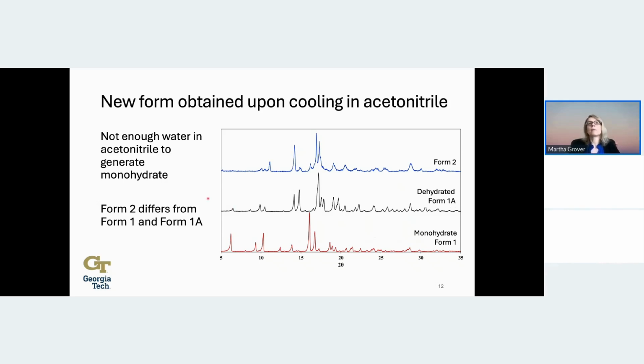So we knew from the beginning that although when we dissolve form 1, there is water in the acetonitrile, it would be a very low concentration, and therefore extraordinarily difficult to get all that water back into another monohydrate. So that was the original rationale here: to have a non-aqueous solvent to avoid forming a hydrate crystal. But indeed, we created what we call form 2 and characterized it with XRD.